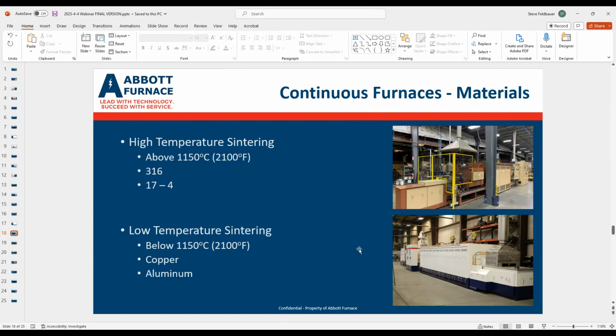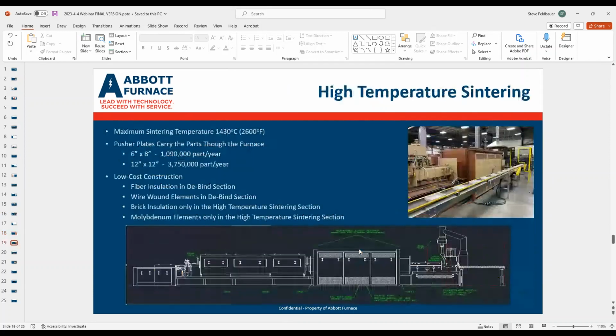And there's a reason that I point this out, okay? When you look at the high temperature sintering furnace, it easily goes to 1430, 2600 degrees to process your materials. We can do, like I say, a little over 1 million parts on a 6x8. If you need to go higher in volume, naturally you could go to a 12x12 pusher plate, and that would be in excess of 3.5 million parts a year. It is a low-cost construction with fiber insulation and wire wound in the debind, and brick and moly in the high heat.